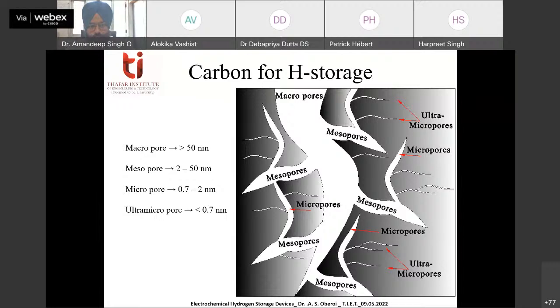Now, diameters of the pores which are greater than 50 nanometers are referred to as macropores. From 2 to 50, these are mesopores. 0.7 to 2 nanometer, micropores, and less than 0.7 nanometers are referred to as ultra micropores. Ultra micropores are the particular pores which are responsible for arresting the hydrogen molecules under the influence of van der Waals forces. Now, if you see, the smallest diameter pores are shown on the right side. They are marked as ultramicropores, right?